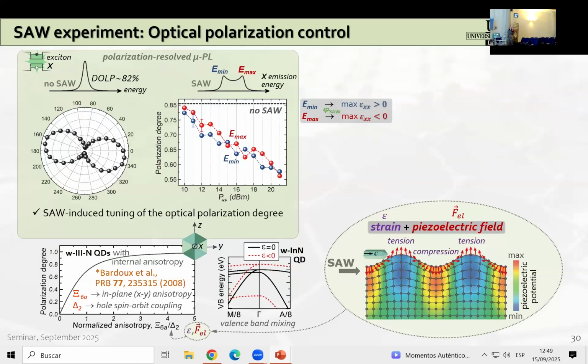So we have also seen that using our acoustic waves, we can tailor the initially high polarization degree of the emitted photons, either from exciton or from bi-exciton. Here I showed the example of the exciton. And as you can see here, at the acoustic phases at which the transition energy of the exciton has the minimum or maximum value, we observe a reduction of the polarization degree up to some 30%. So we are basically limited here by the maximum acoustic power that we can apply to the IDT. Otherwise, we could go even further.